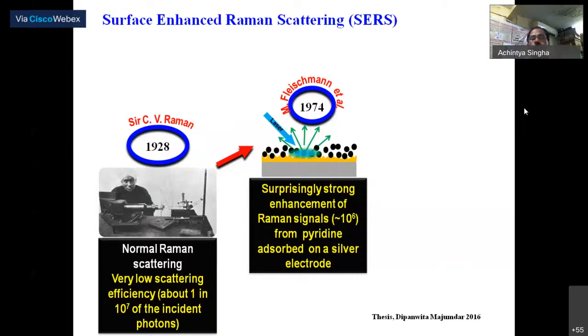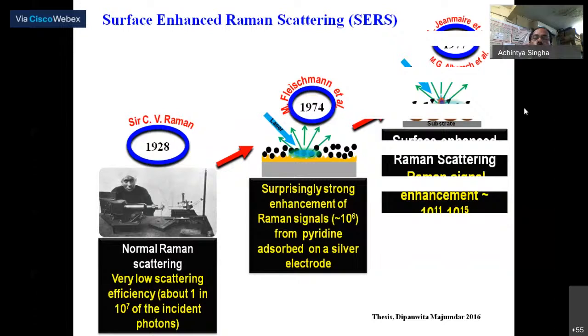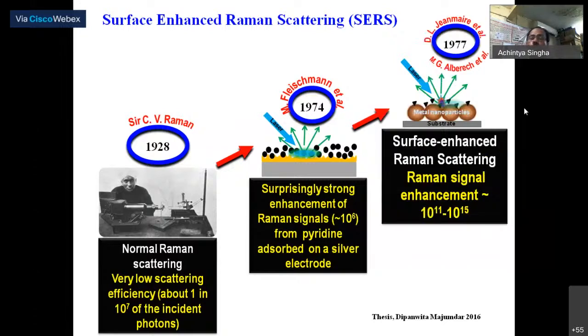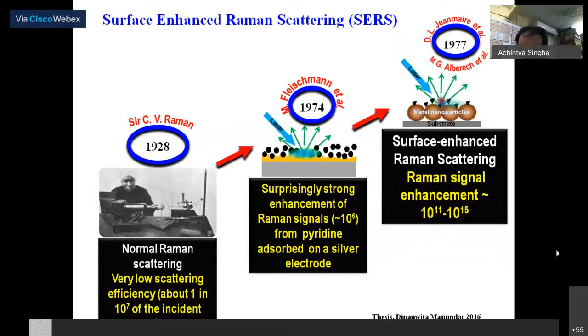But after 3 years, you can see these two groups independently found that this enhancement is not due to the surface. This huge enhancement, of the order of 10 to the power 11 to 15, is not due only to the surface area increase. So they said that this enhancement is due to two effects. One is the electromagnetic effect, another is the chemical effect.